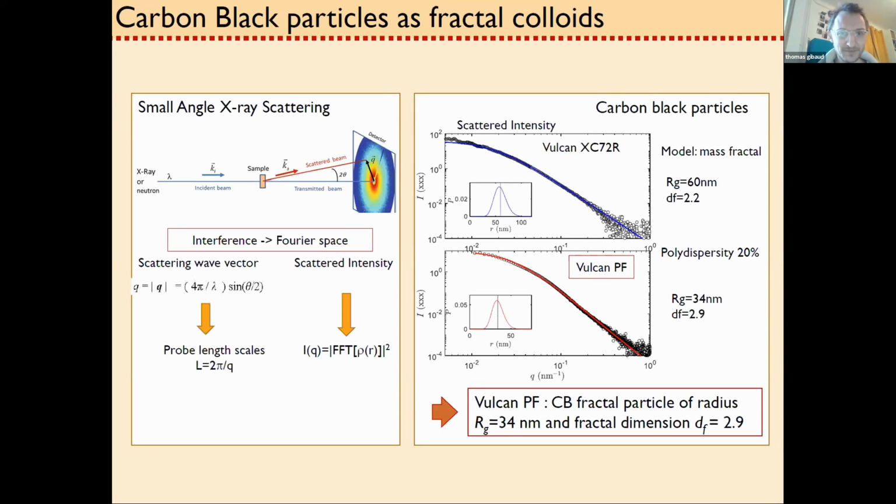And I use the small ones basically because at some point I want to do SAXS. And SAXS works better with small particles because then you can eventually measure the size of larger clusters. If you start with too big particles, you're out of the SAXS range. So SAXS, what is it? You shine X-ray on your sample, it's scattered by the sample, and you collect the data on a camera.